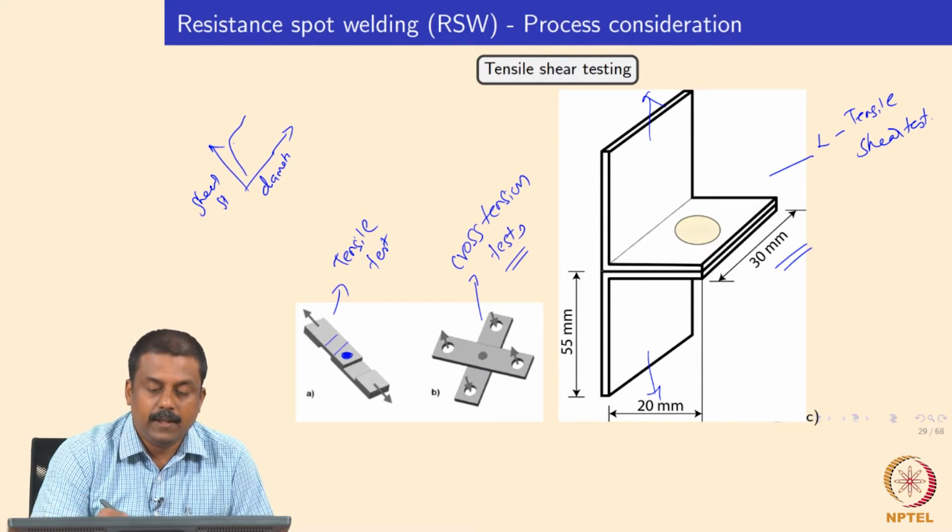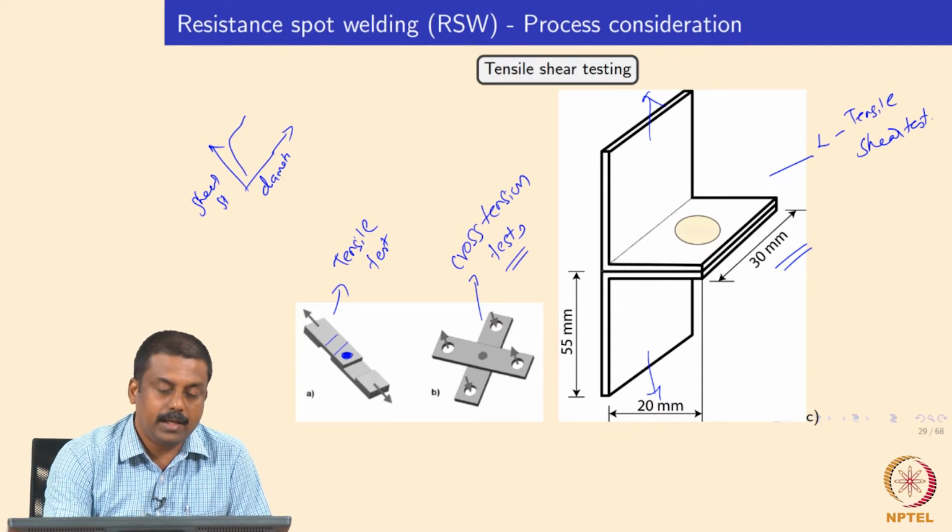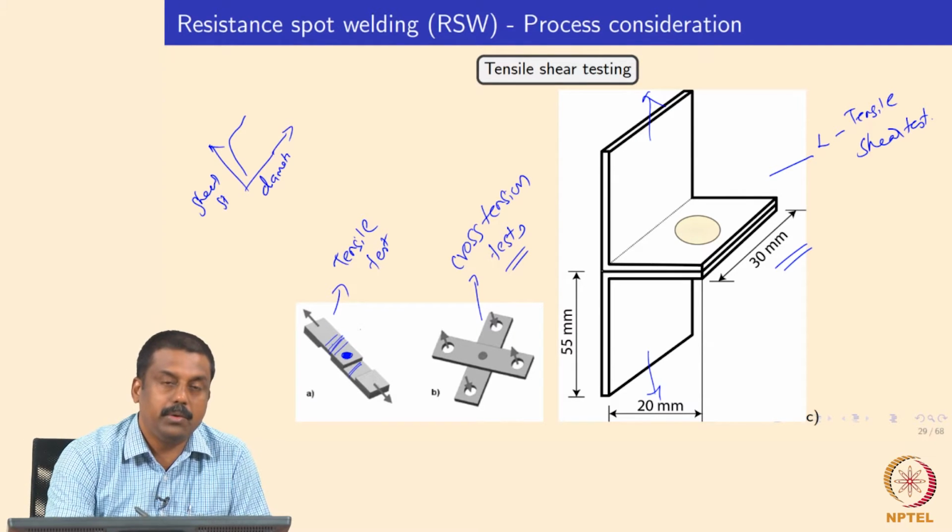Shear strength. There are some issues in conducting a tensile test in a low overlap configuration, because we never know whether the load is applied only to the weld. So you may also see the base material deforming, and so the shear strength you are measuring is not exactly the strength of the weld.